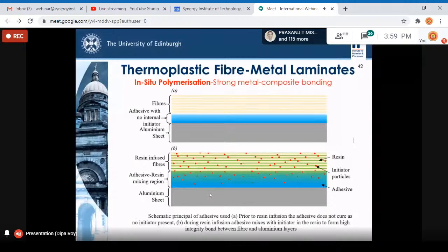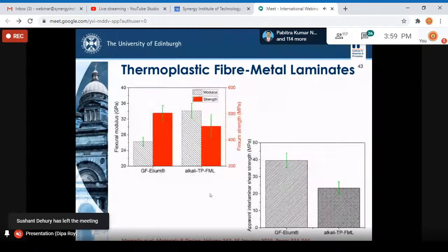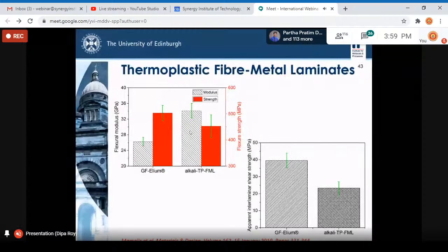doing this. And we measured some mechanical properties. These were some of the properties, from preliminary studies. This is already published in this paper. So here the metal was alkali treated, and we compared the flexural modulus and the flexural strength with the standard glass fiber acrylic composite. And we saw that the modulus was quite high and the strength was slightly lower.